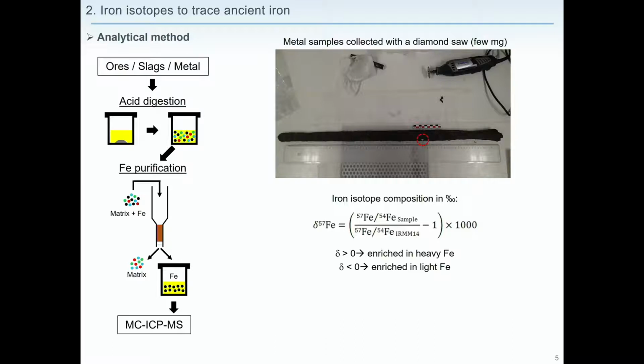Once collected, all these samples are digested in concentrated acid. Then the iron is purified from the rest of the matrix with a classical chromatography on an anion exchange resin. And then this iron is analyzed using a mass spectrometer with multi-collection. We express the iron isotope composition in per mil with a delta index, here delta 57 iron. It's the ratio between 57 and 54 of the sample compared with that of an international standard. If this delta is positive, we have a composition enriched in heavy isotopes. If it's negative, the composition is enriched in light isotopes.